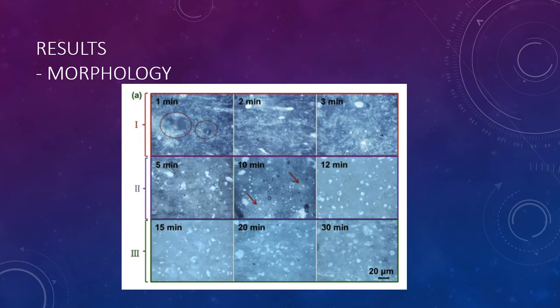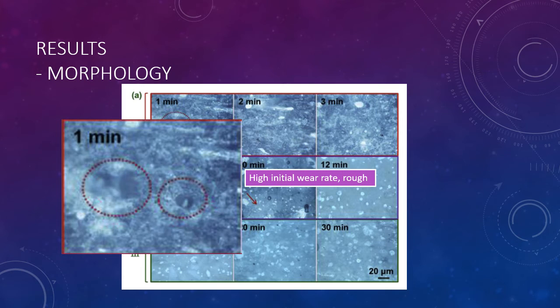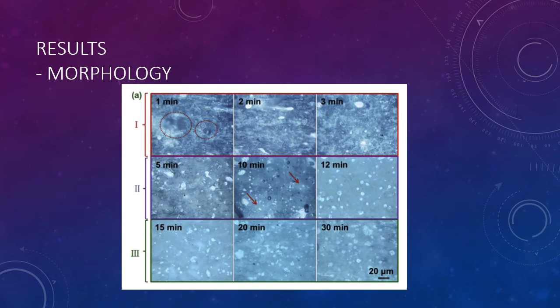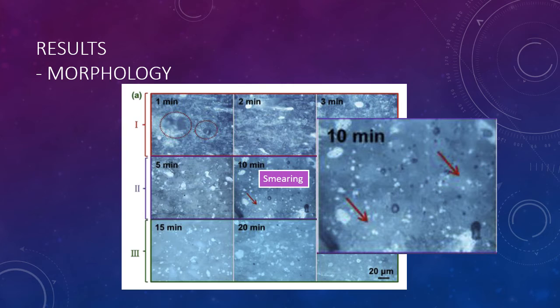For the morphology, we did it under the polarized light optical microscope, so-called POM. For the 9 figures taken, we can see there are 3 rows. The first row is the running-in phase, the second row is the transition phase, and the third row is the steady state. For the running-in phase, at the first minute, we have a high initial wear rate and a rough surface of the sample. So you can see there is a very big dark spot on the figure. And at the 10th minute in the transition state, because of the continuous sliding motion between the contacting surfaces, we can see a smearing effect of the LCP nanoparticles throughout the area.